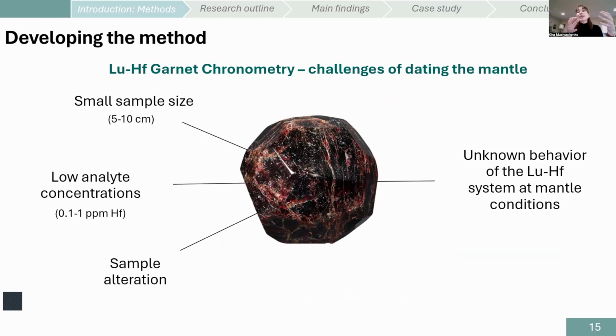So if you're lucky, it's up to 5 to 10 centimeters. I've worked with pebble-sized samples, really annoying, but that happens as well. On top of that, mantle garnet is really, really depleted in a lot of major and trace elements, particularly in hafnium. So we have very, very low concentrations of analyte. And we can't compensate for that by processing more of the sample because our sample size is small to begin with. And if that's not enough, we also have sample alteration.